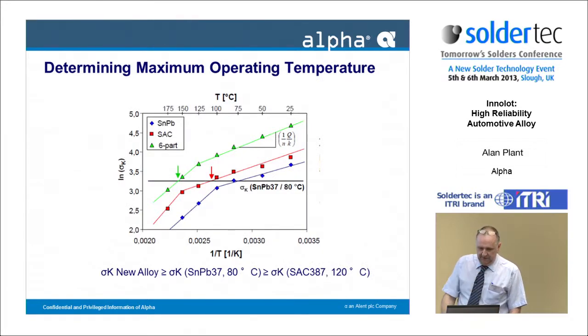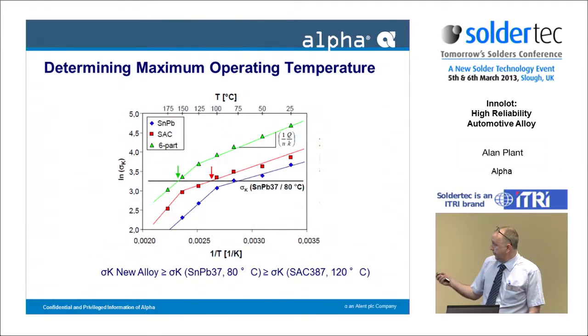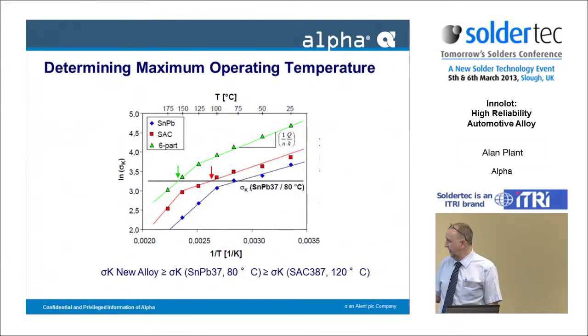The whole idea of this was to design an alloy with a maximum operating temperature, which had been targeted at being 150. So if we look now at the creep resistance, here we've got the figures for the tin lead alloy, and data that the end users had, they were quite happy with the tin lead performance at 80 centigrade. They would get a typical similar performance from the SAC alloys up to about 115, 120, somewhere around about there. So the idea was to get the same creep performance out of the 6-part alloy at an operating temperature of 150.